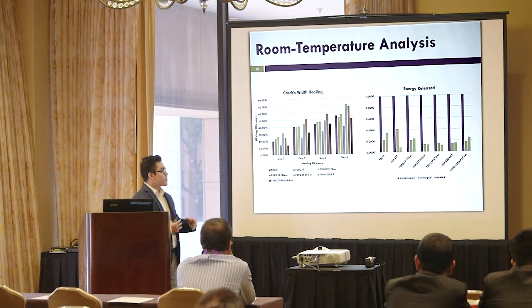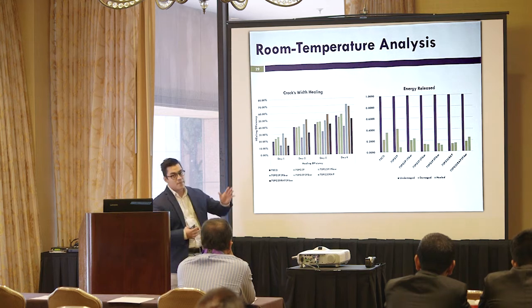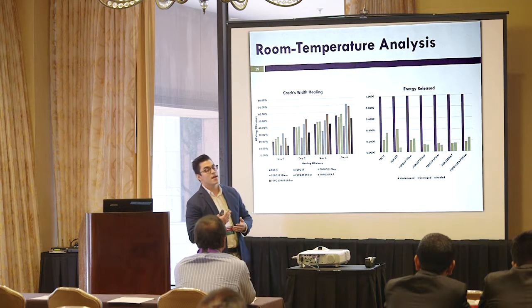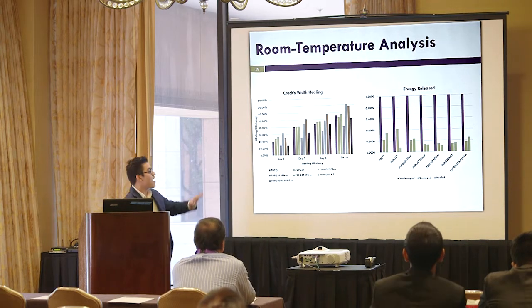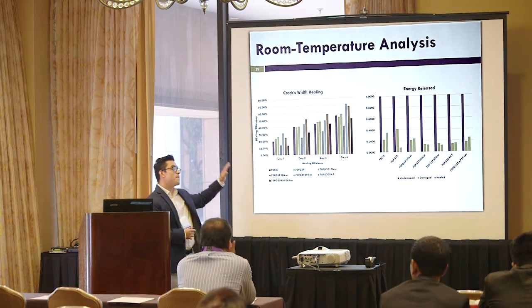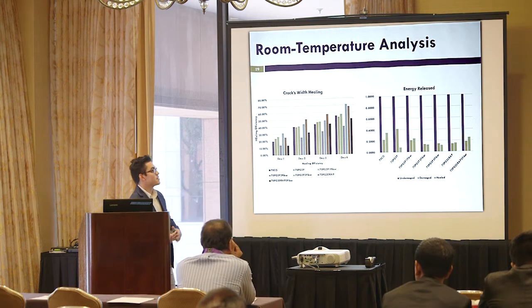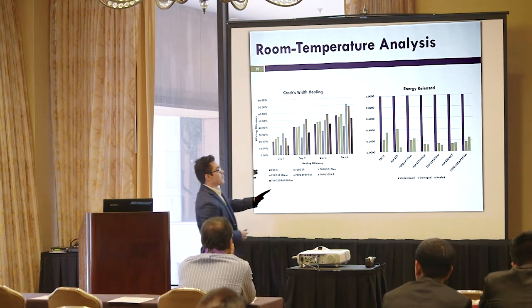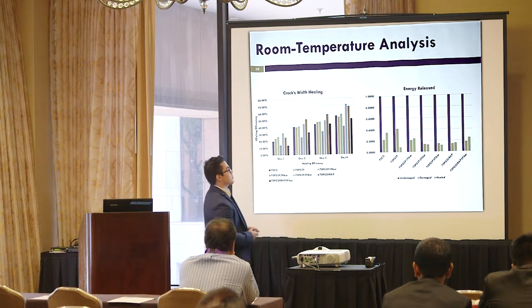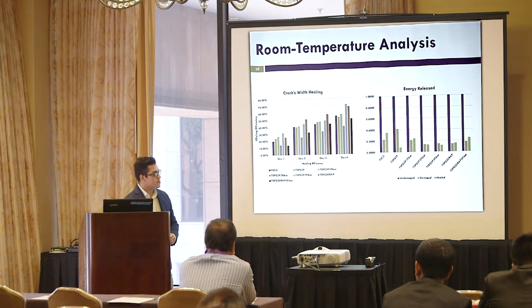For the crack width healing efficiency at room temperature, we observed that the mixture containing 5% RAS plus 5% fibers had the highest healing efficiency based on the crack width analysis. However, that particular mixture didn't recover that much strength based on the fracture energy analysis.